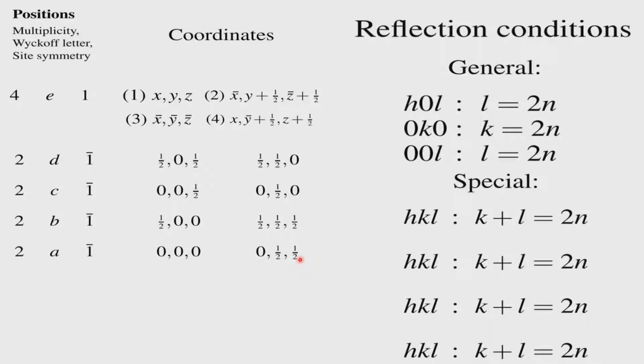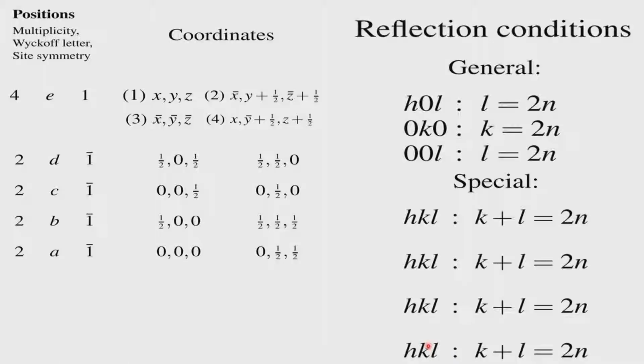Now what is very interesting is that only if the atom is sitting at these positions, you will have this, if it is an atom. If it is a molecule, only the molecule's center of symmetry will sit there, and the center of symmetry of the molecule need not have any atom. There may be one atom in the molecule which may sit there. For example, it could be an organometallic compound. The metal atom may sit at this position, but the fact that the other atoms are sitting in other general positions will not give you only these.